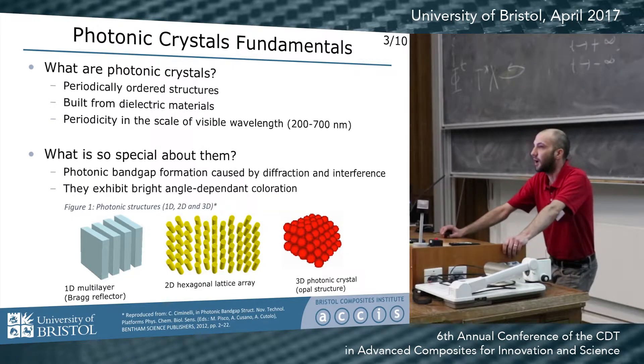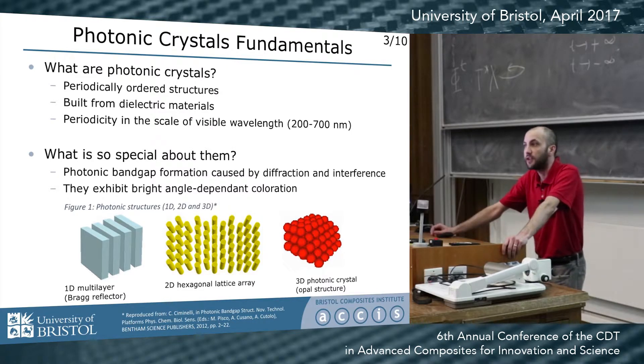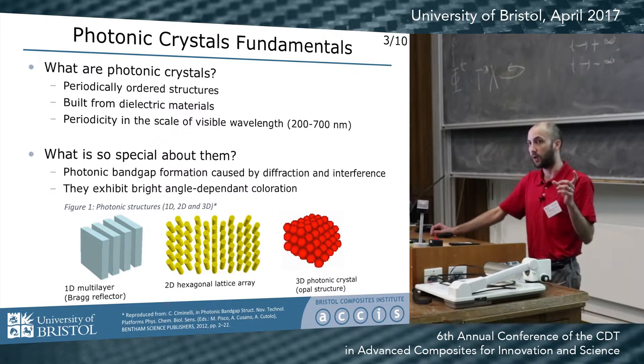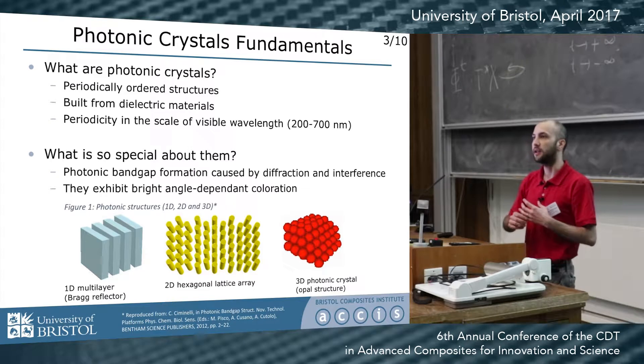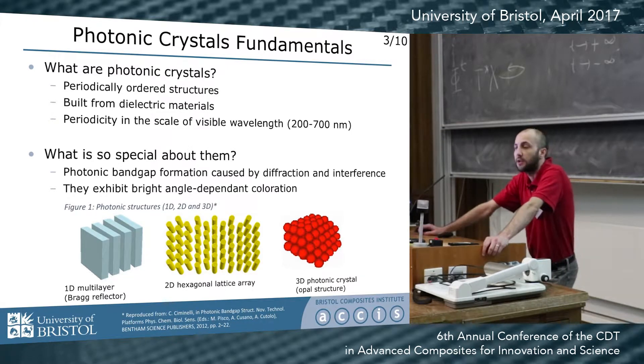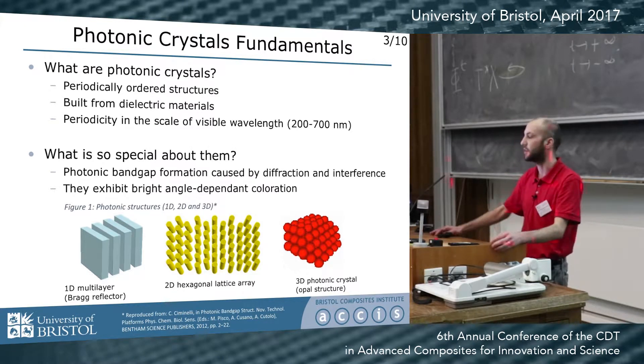Photonic crystals are periodically ordered microstructures built from dielectric materials. The periodicity of these materials is in the range of the visible wavelength. Diffraction and interference caused by the periodic structure generates a band gap in the photonic structure, similar to the electronic band gap in semiconductors.